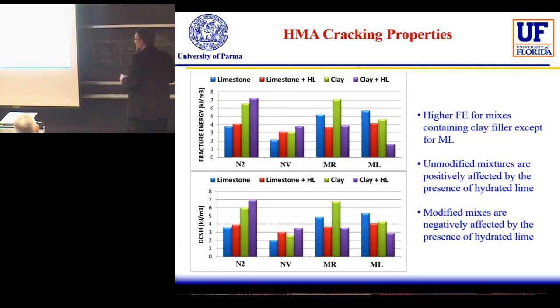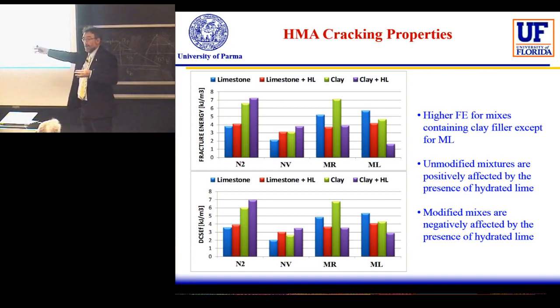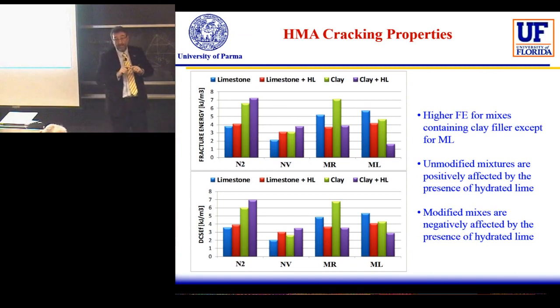With the fracture energy, something is more clear, but again it is difficult to find a clear path. The clear message is for sure that the filler makes a difference. So changing the filler, we have different behavior of the material. It's something strongly related to the physicochemical effect that the filler has with the bitumen, because we are changing nothing in terms of the internal structure of the material.